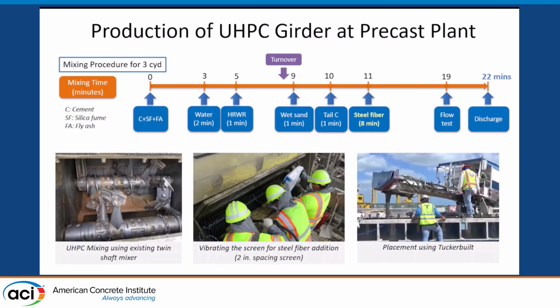We did hold back a little bit of the cement because it is such a dry mix. We needed some of the water from the wet sand to combine with the cement, and we didn't want it to be too dry at the beginning as we initially added water. So that was the reason for what we call the tail cement. Then we're adding steel fibers. This took about 8 minutes, and that was about as optimal as we could get in this situation where we didn't have any kind of automatic conveying of the fibers into the mixer.